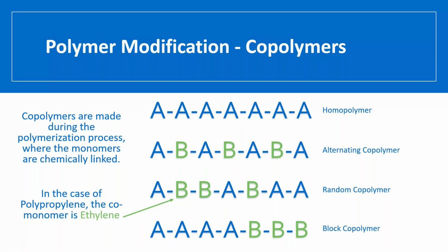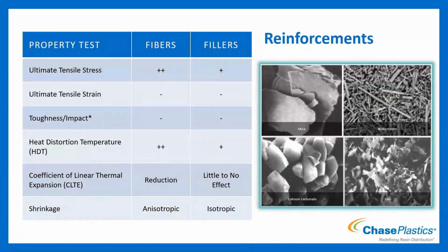So there's plenty of areas where this can be done to achieve new and different properties. Propylene homopolymer tends to be a little higher in crystallinity, with better stiffness and strength performance. Adding ethylene allows for better low temperature impact and improves impact performance. So your copolymer propylenes have higher impact performance, are a little more flexible, but have better impact performance. Depending on what you're trying to achieve - if the homopolymer was too stiff or didn't have the impact you needed - you might look at a copolymer. Each different copolymer will have different performance functions depending on what's being added, but that's the example of propylene.